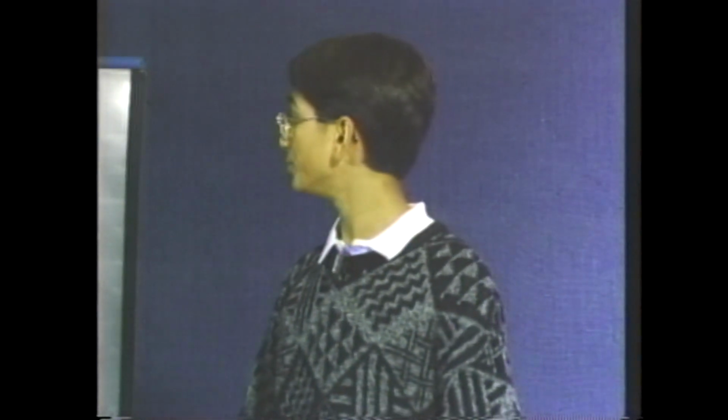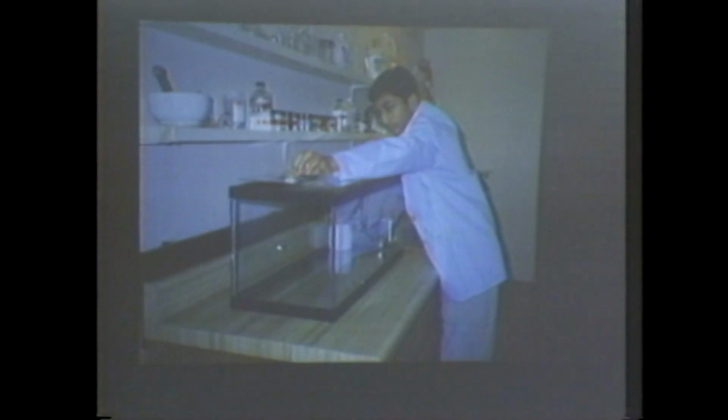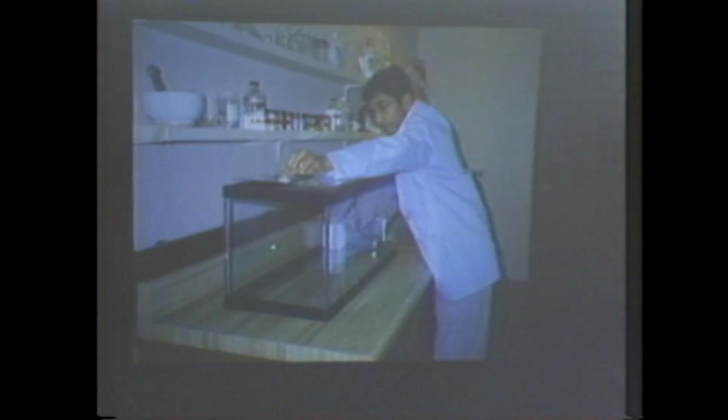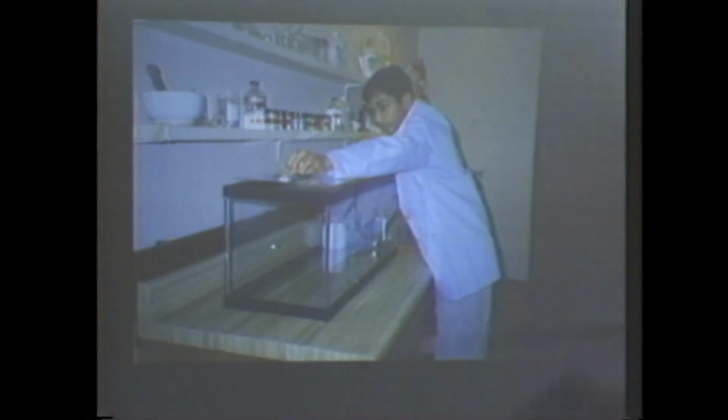I designed a special humidity control chamber using a glass aquarium and a plexiglass cover. The humidity inside this chamber was controlled by placing 150 grams of anhydrous calcium chloride inside an open wide-mouth bottle and placing this bottle within the aquarium. All test samples were conditioned inside this chamber before static measurement.